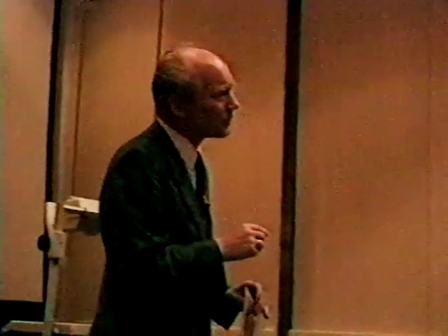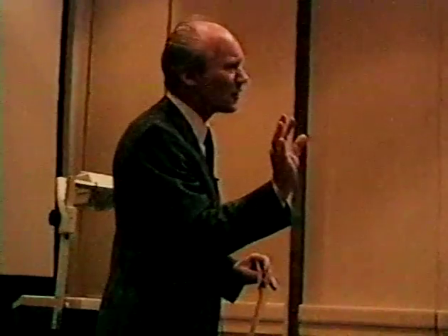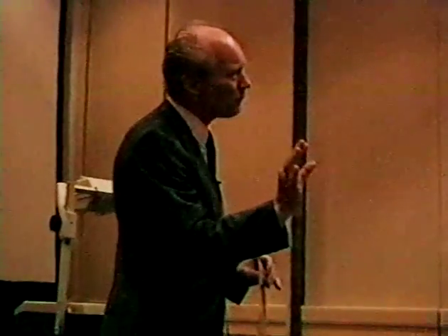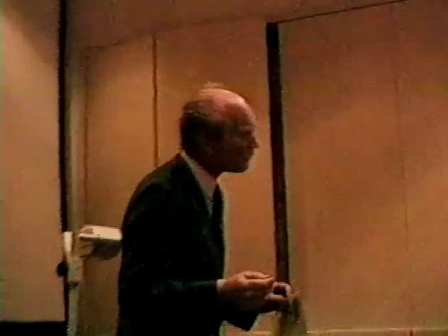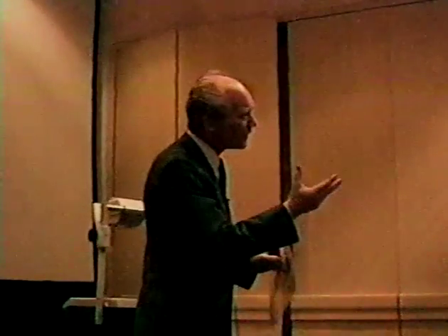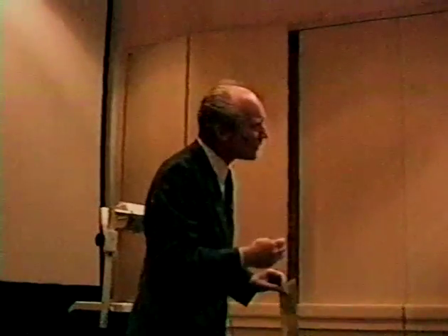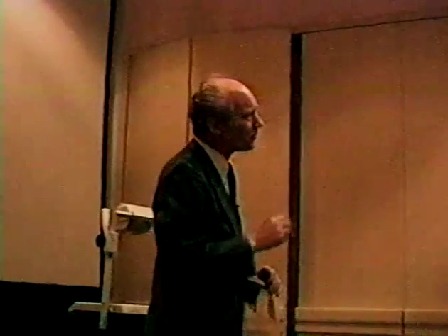You only can say that the lattice, you can just deform the lattice rather easily. Auger did a very interesting experiment that showed that the cone had really a circular cross-section. So it is not being bounded by crystallographic planes, it's not faceted. And you only can have that because the graphite layers, you can turn them around, and you get a circular cross-section of the graphite layer, and that brings about a circular cross-section of the metal part. So Auger did very remarkable work about that, very good work.